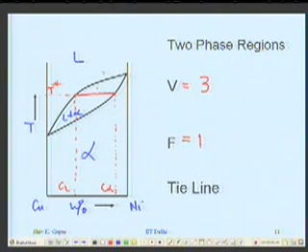And then two of them have to be in equilibrium. Okay? Two of them are in equilibrium at a constant temperature only. This one is in equilibrium with that at this temperature. Similarly, at another temperature also they can be in equilibrium. I have changed the temperature. But what is in equilibrium is this composition of the alpha phase and that composition of the liquid phase, which are different from these. It is not the same equilibrium. It's a different equilibrium. At some other temperature, let's say lower temperature here, this is the solid which is in equilibrium with this liquid and the temperature is different.